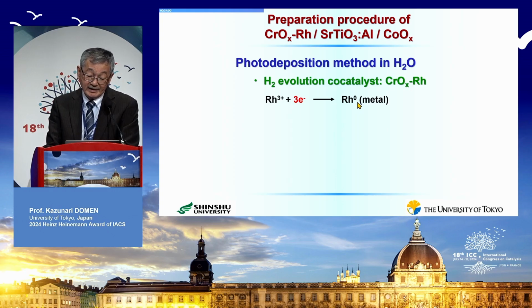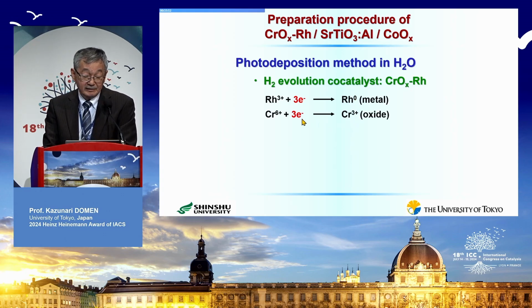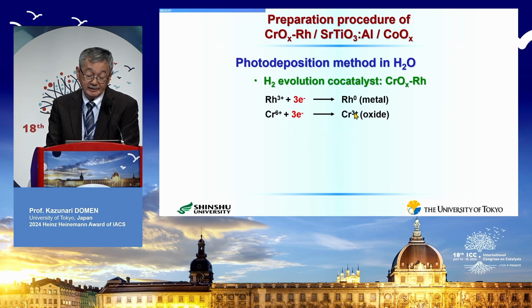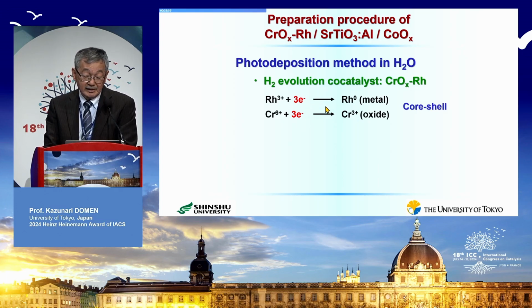To prevent such a reverse reaction, we coat these metallic rhodium nanoparticles with chromium oxide, hydroxide. In this case, again, we use photoexcited electrons to reduce chromium-6+ into chromium-3+. By these two reactions, we can construct a core-shell structure. And in these two reactions, we use the photoexcited electrons. So these reactions are so-called photoreduction reactions.